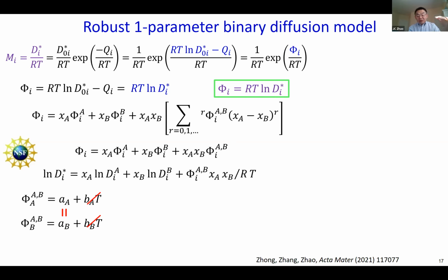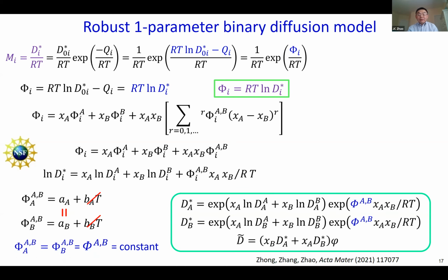Some of this data covers from 800 degrees to 2000 degrees, a 1200 degrees C temperature span. Most systems don't have that wide a temperature range. Even for those systems, none requires this one. So that's the basic message. Now, if you really want to use 2 parameters, go ahead. But we found that the 2 parameters can be equal and still do a great job. If you use that, then the diffusion coefficient equation becomes really, really simple.